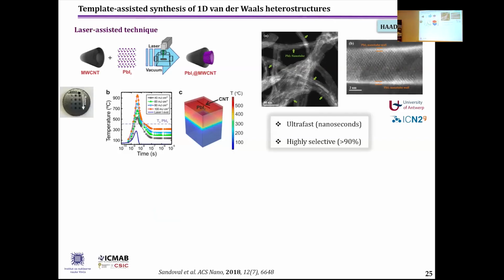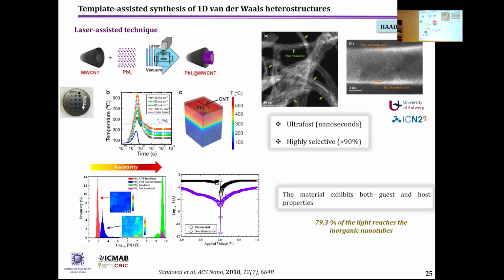So following with the tuning of the ratio of the structure which are confined inside the material, we also developed a new technique in collaboration with Angel Perez, in which we use laser to selectively prepare hollow heterostructures inside carbon nanotubes. With this technique, which was ultra fast, we were able to obtain up to 90% of tubes against the other approaches where we obtain mixtures between rods or nanowires and nanotubes. So this is a very efficient protocol to selectively prepare hollow heterostructures.